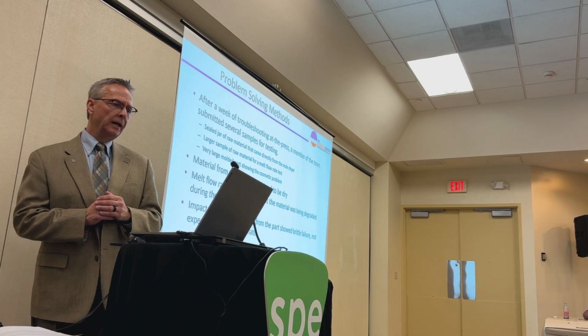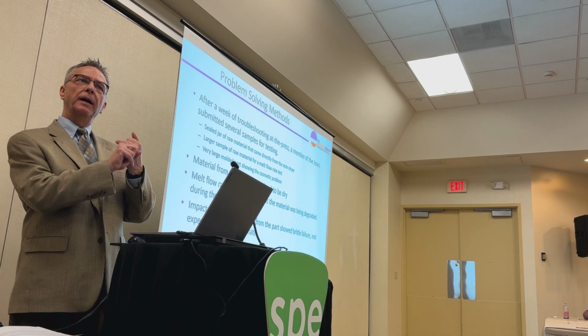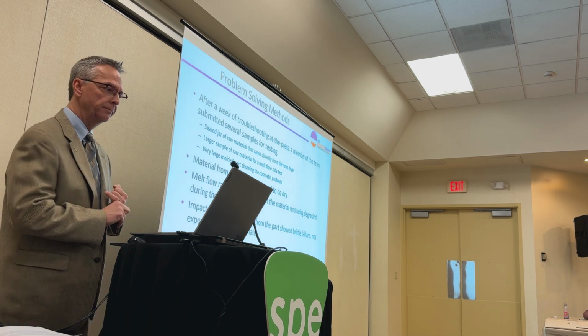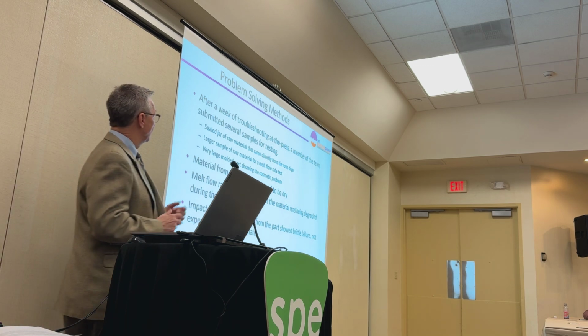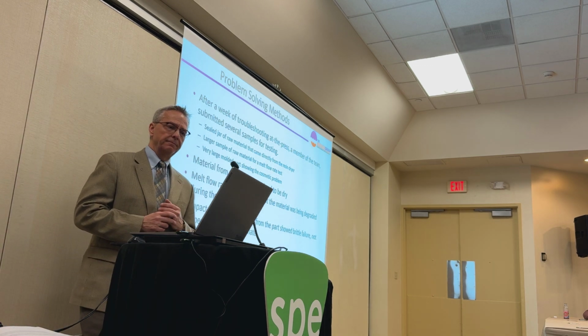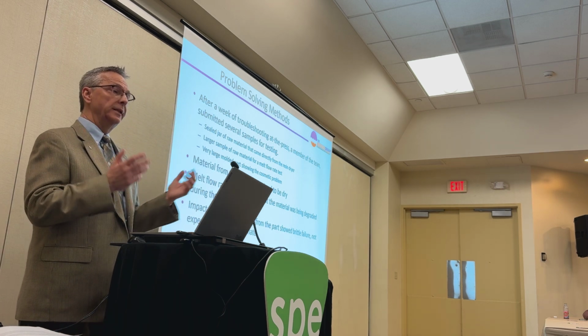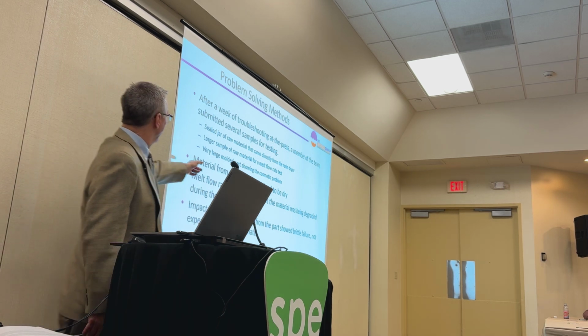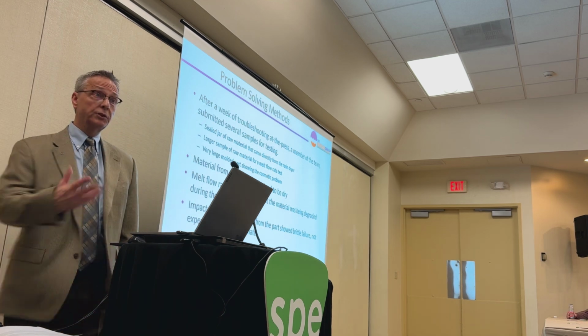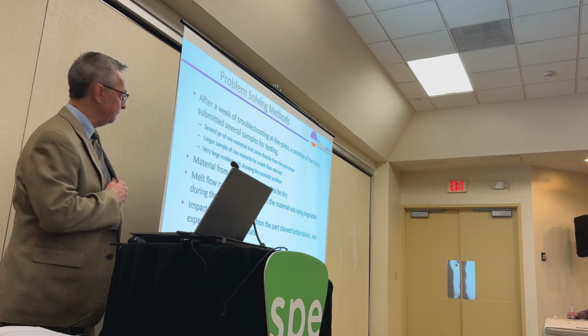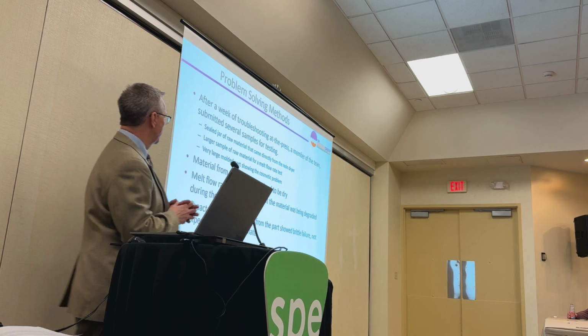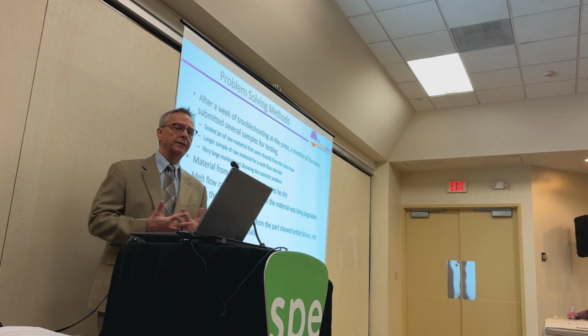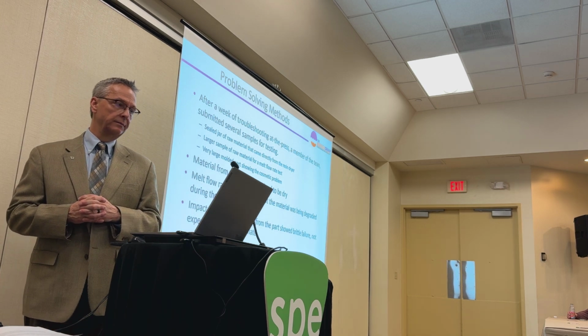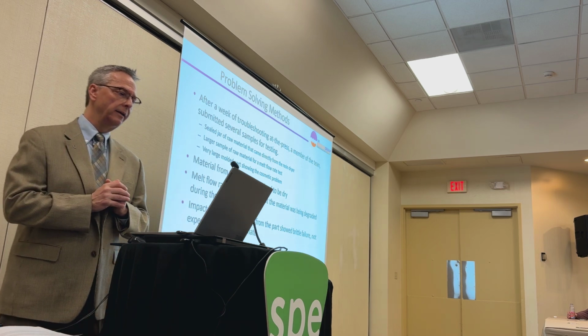They sent a sealed jar of some raw material that came right out of the dryer, because what did they suspect? The material was not being dried properly. They sent a larger sample of raw material for some melt flow rate testing, and they sent a very large part showing these cosmetic defects. Well, some testing showed that the material from the dryer was dry. It wasn't a drying problem. Melt flow rate testing showed that the material was being significantly degraded during the injection molding process. Okay, but not because it wasn't dry.